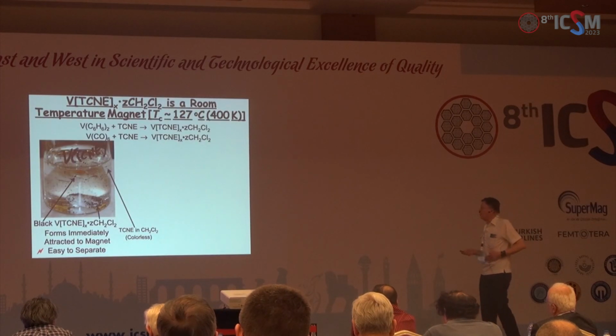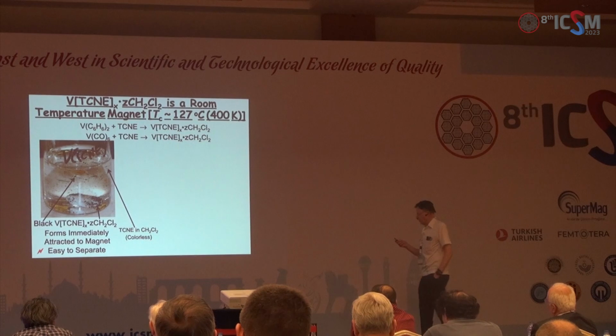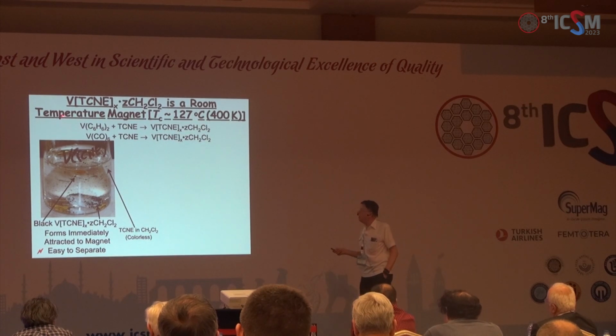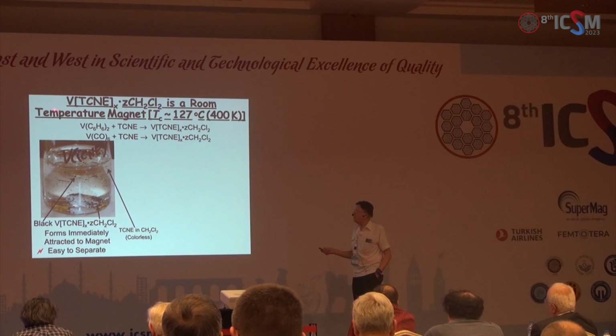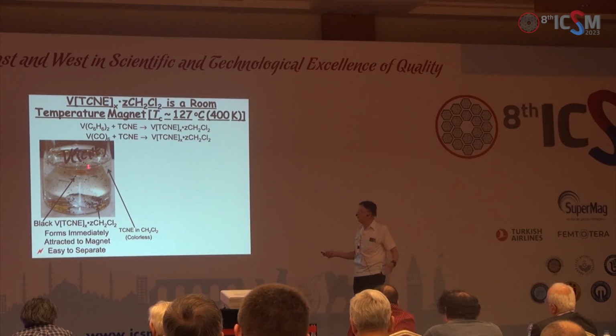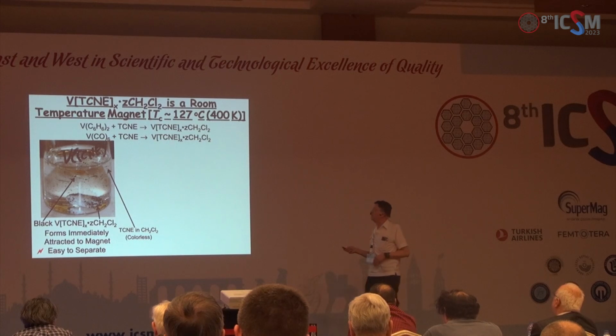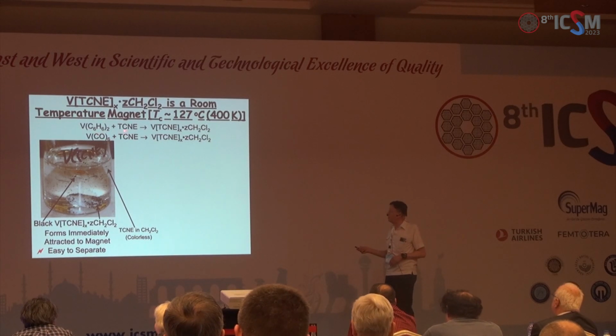So we did a little funny chemistry here. We took the iron out and put vanadium in. We took the 5-membered ring out and put a 6-membered ring in. Bis-benzene-vanadium plus TCNE, also in the same solvent dichloromethane, gives us a material that has no benzene in it. Nowadays we make it from vanadium carbonyl and TCNE—it's nominally the same structure.